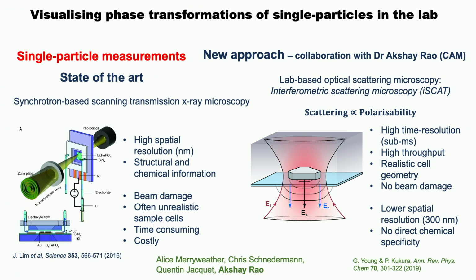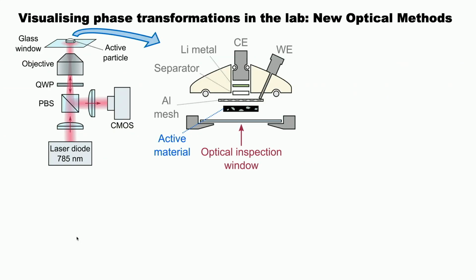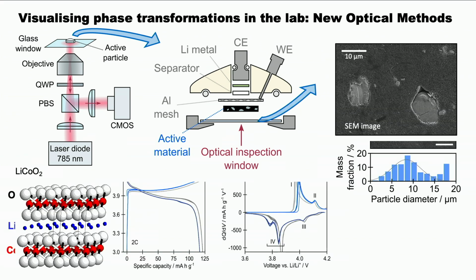So actually, I hypothesized that we should maybe be able to use this to follow how ions went into material. So that's the way we went into it. This was a story of 2020 or end of 2019, and I said, let's keep it really simple. Let's use a particle that's big and we know what's happened. So we took our friend lithium cobalt oxide. The student Alice Merriweather made some beautiful experiments where she diluted the lithium cobalt oxide in a carbon matrix. We just took a Raman microscope cell, and so you can see the basal plane, the top of the lithium cobalt oxide, and the electrochemistry is doing its normal thing.